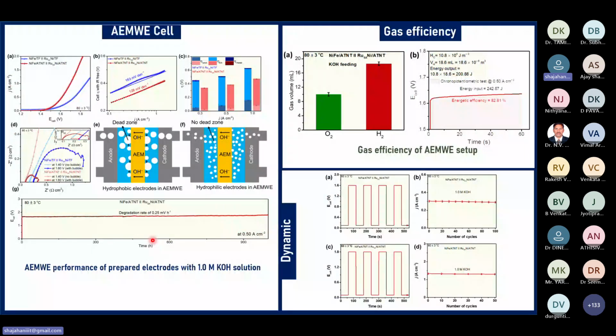So we also did the half-cell measurements, so that is not important to discuss for the time being. So directly we will go to the AEMWE experiment. In the AEMWE experiment also, when we used the already prepared nickel Fe as anode and ruthenium single atom doped nickel as a cathode, we got better performance than the same catalyst on the other substrate. So stability also, over 1000 hours we observed. Gas efficiency initially was 79 or 78% with the KOH. Here we got 82.81% with the KOH. So the gas efficiency also increased. And it has better stability during fluctuations. We also observed this with our anode and already prepared cathode.